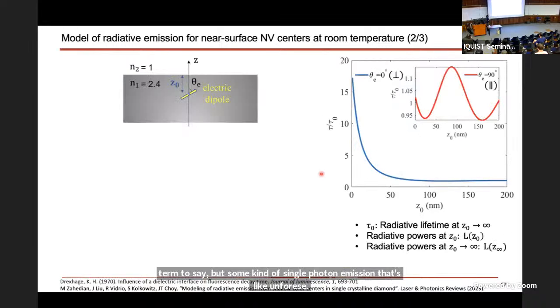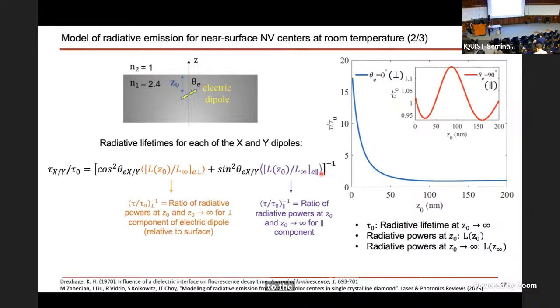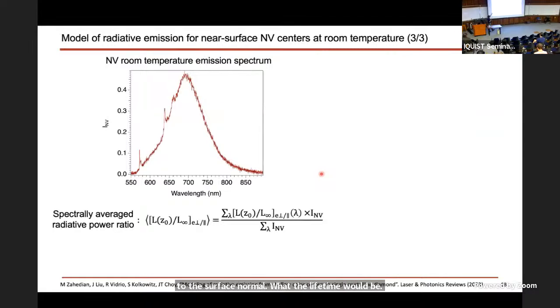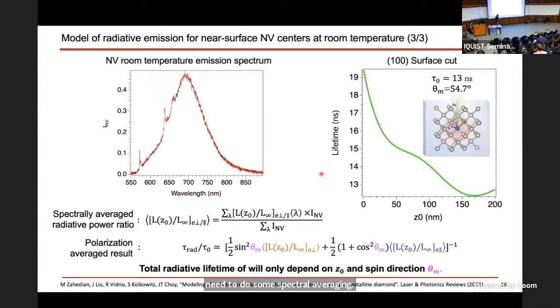Okay, so you can then model this radiative emission based on the model I just mentioned. Skipping over the details, what we do is first calculate, for near-surface NVs, as a function of depth, how the perpendicular and parallel components of the dipole behave as you approach the surface. Then you apply geometry to figure out, for the actual dipole with that weird orientation of the spin relative to the surface normal, what the lifetime would be. One more thing: as I mentioned, the NV emission is broad, so you need to do some spectral averaging, and then finally a polarization average. But then what you get in the end is this.